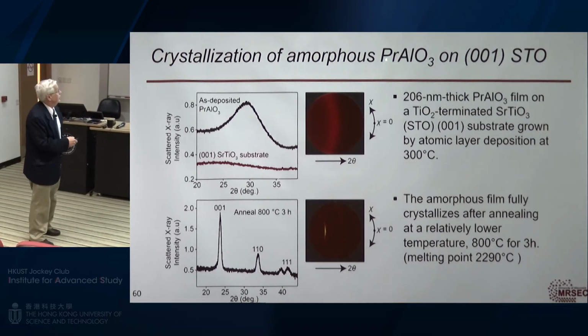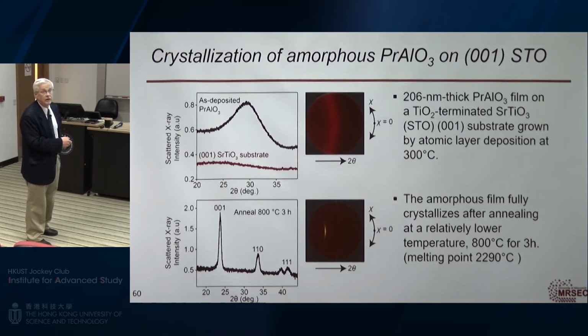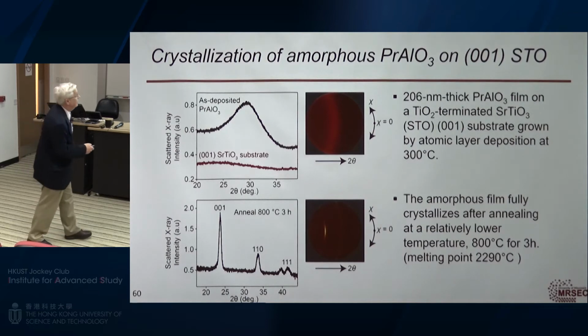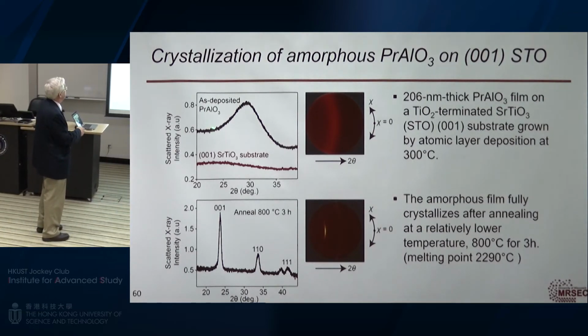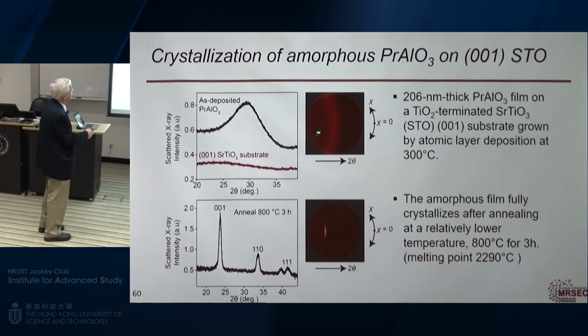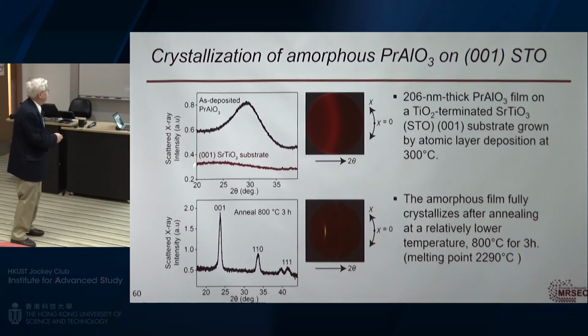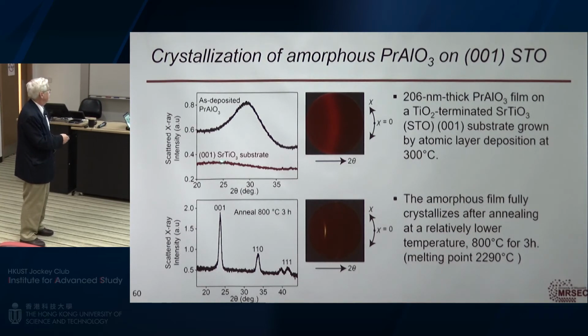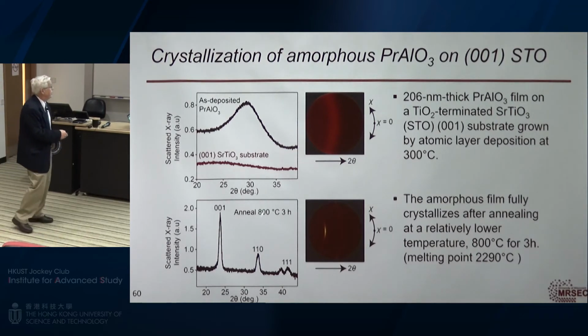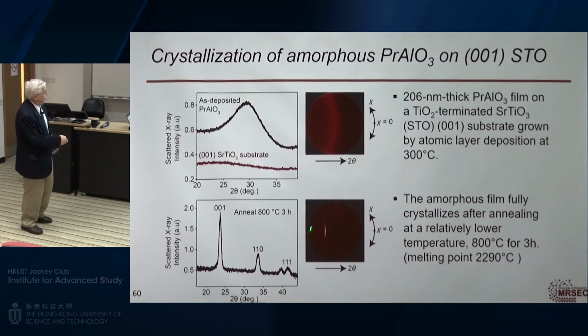So we basically put down praseodymium aluminate. This is something that's used for making two-dimensional electron gases in complex oxides on strontium titanate. And we deposited it, this is by ALD, and you can see that this is an X-ray micrograph. It's an amorphous structure. It is completely amorphous, and this is the same scan of the substrate, where there's no Bragg peak. And you can see that this signature here of the amorphous structure will be used to tell us whether it's crystallizing or not. If I take it and anneal it at 800 degrees for 3 hours, it becomes completely crystalline and epitaxial, and that's shown here in this area detector.